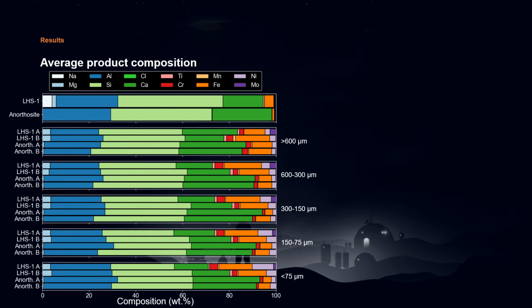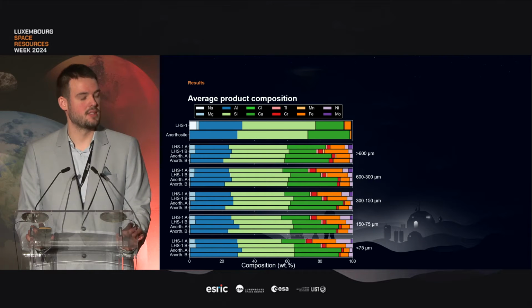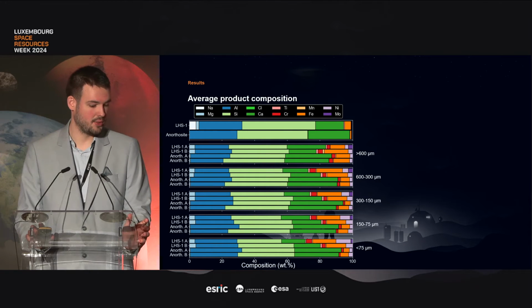And from now on, we're going to look at the metallurgy, so at what's actually in the product, at the composition. So this is the data we got from the average composition. You can see at the very top are the 2 feedstocks, LHS1 and anorthosite. Then moving down, we have the 5 size fractions, and for each size fraction, we depict the 4 experiments that were performed. Here, the main metals we can track are aluminium in blue, silicon in light green, calcium in dark green, and then the iron in orange.